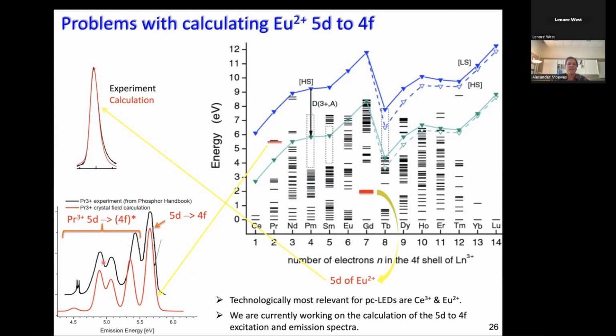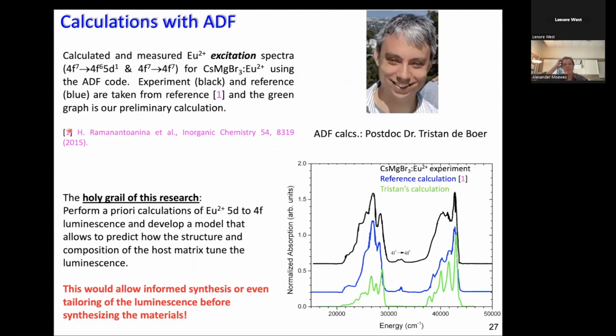So what we do is we now measure the optical excitation spectra, then try to calculate these, and then hope that the set of parameters that we used to determine the system, and that allows us to calculate good excitation spectra, that parameter set will hold, and then will allow us to also predict these spectra a priori. That means before you do the calculation. So that is, so to speak, the holy grail, and Tristan is working on this.